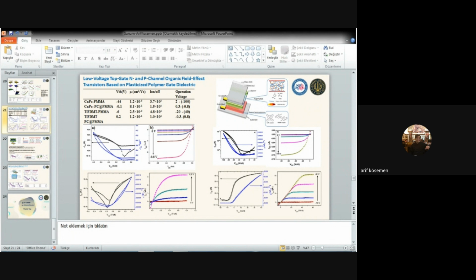Also, we add some new information in this study, because copper phthalocyanine and P3HT are p-type organic semiconductor materials, and we also use n-type organic semiconductor materials with this gel-like PMMA approach, because we want to see whether this approach can work only with p-type materials, or both p and n-type materials. And these are results, output and transfer characteristics for both materials. The gel-like dielectric worked very well, and we can get a transistor under 0.8 volt with good transistor behavior. You can easily see the linear regime and saturation regime from these graphs.